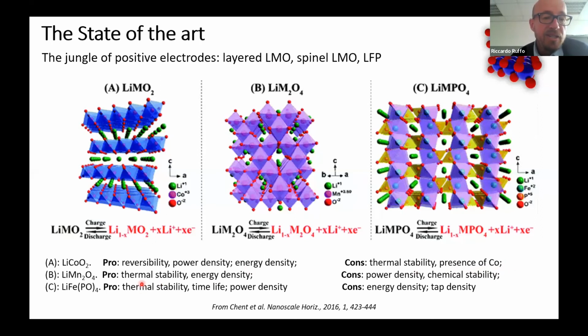In the case of spinels, they have better thermal stability and good energy density. However, the power density is lower. And the use of manganese in many of these spinels also introduces a sort of chemical instability due to the Jahn-Teller effect. Finally, we have lithium iron phosphate, which has very good thermal stability, very good lifetime, and power densities, and can be used at very high current. However, the voltage of this material is lower than the other 2 classes by about 500, 600 millivolts. So this affects the energy density.